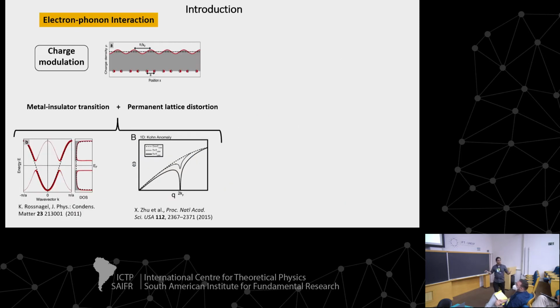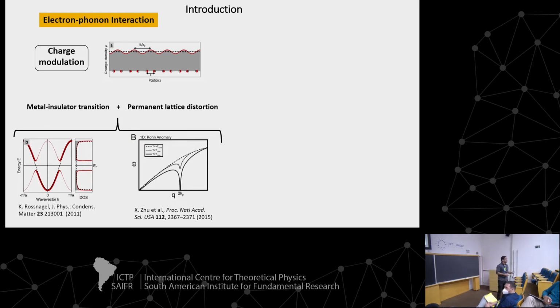When we have electron-phonon interaction, this kind of interaction can lead to charge modulation. Basically, this coupling can create regions with more electrons and less electrons, in such a way that you have long-range order. And this leads to a metal-insulator transition and a permanent distortion in the lattice.